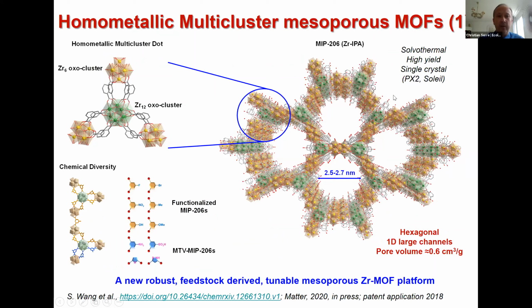Actually, it's a new zirconium mesoporous solid, made under solvothermal condition, in high yield and formic acid condition, with the structure from single crystal. So it is mesoporous. It's a hexagonal structure, with a large channel of 2.6 nanometer. But the interesting feature here is that we use two building units, Zr6 cluster and Zr12 oxo cluster. So it is a homometallic multi-cluster MOF.